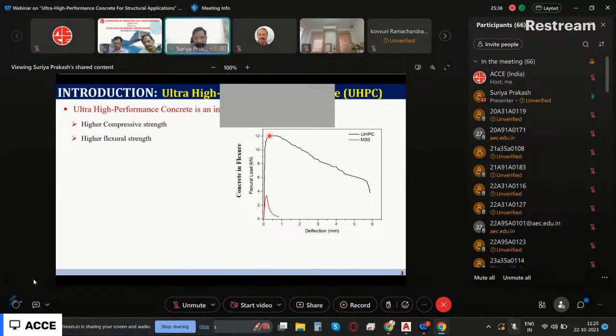And also when it is failing, you can see that suddenly the capacity is dropping in this M50. But here the capacity is dropping very, very slowly, very gradually it is decreasing. So that means this material can sustain high strength in flexure, bending. Also, right after cracking, it will not fail. It will give away its capacity very slowly. That's what we want as a structural element. Soon after it develops a crack, we don't want failure. It should give sufficient warning before we can look at some intervening techniques. Okay, so this is a big advantage.